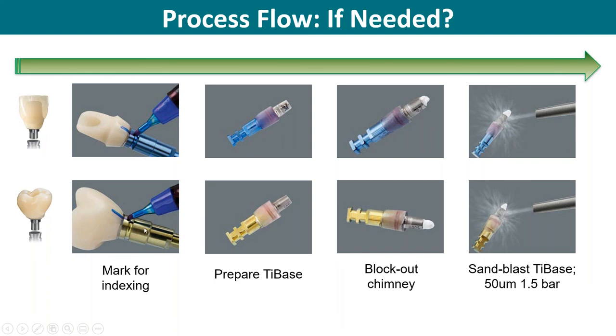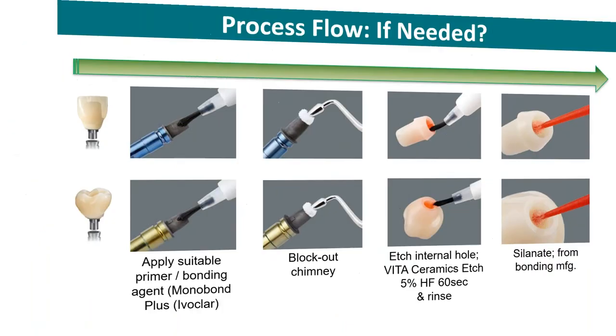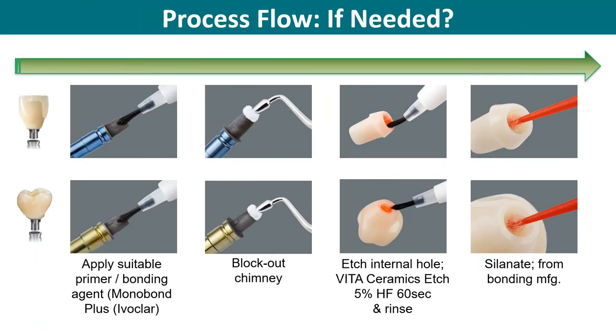We mark it up. We place it on like a replica, analog, however you want to call that. We then cover up the chimney. We sandblast it. Once it's sandblasted and textured, we're going to come back and we are going to use a monobond plus or any other primer type material. So we sandblast it, we clean it, we, in a sense, silanate it using a primer. And then we take the restorative material, whether it's cement retained, the top row here is all cement retained. This is the process for screw retained.